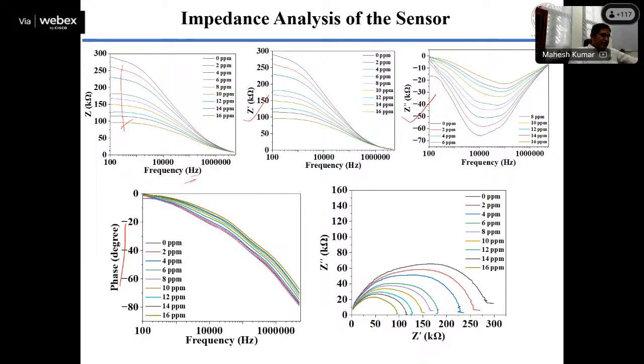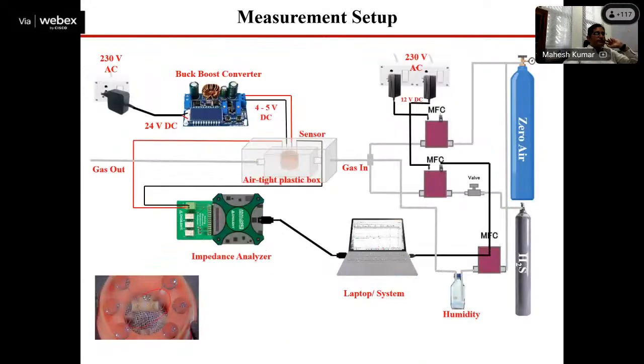If you take higher frequency or lower frequency, the impedance changes, but the change in the phase is almost constant with the frequency. So we can also use the phase. We can measure the phase only, and then we get the information on how much concentration is there. This is simple. Again, we can plot the real part and the imaginary part, and from that also we can make out how much percentage of this gas concentration is there.